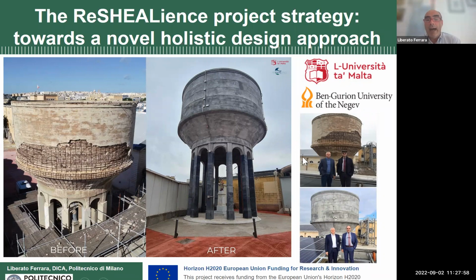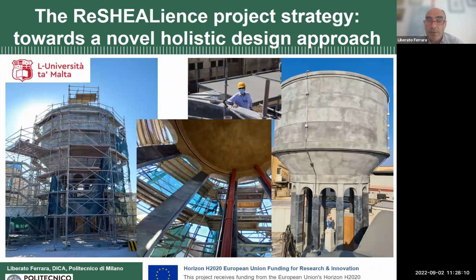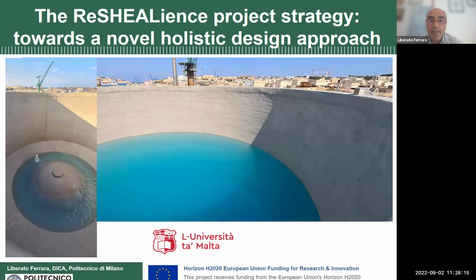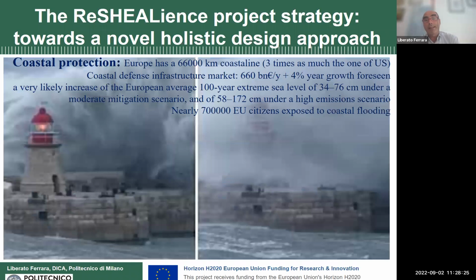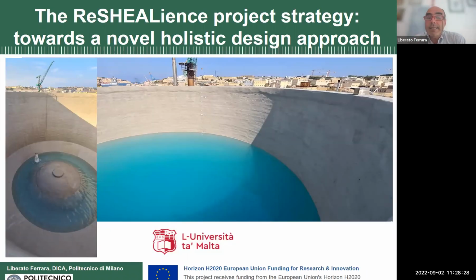And you can see here how it has been now retrofitted. We used a self-compacting UHPC for the columns and the textile reinforced UHPC for the drum. And some images during the construction, it was quite remarkable. I visited it several times, and these are some images of the validation tests in which we filled the tank, and it's now used as a water reservoir by the abattoir of Malta. This is to say that these solutions that we develop are tailor-made for each kind of application.